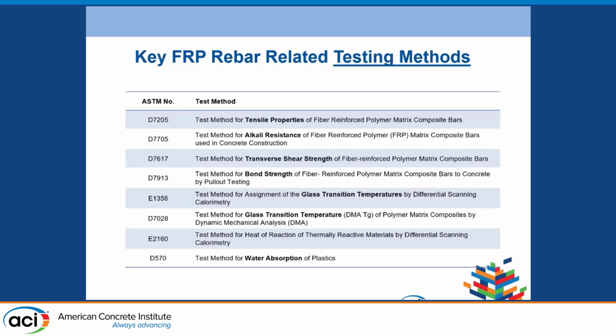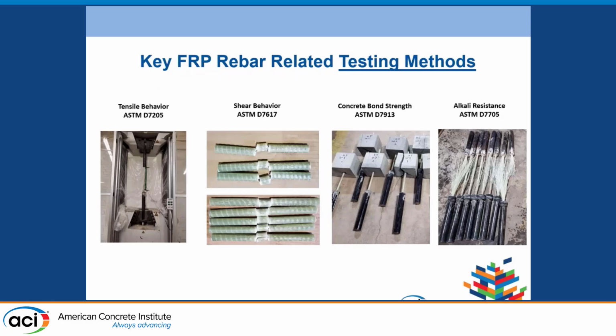And the transverse shear strength testing reflects the interaction between the resin and the fiber. And the bond strength of the rebar to the concrete, by pullout test, reflects the interaction between the rebar and the concrete. The glass transition temperature can be measured by DSC or DMTA. The requirement is over 100 C for the DSC testing method. And the degree of cure can also be measured by DSC. Here we show some imagery for this testing, like transverse shear, concrete bond strength, and alkaline resistance testing.